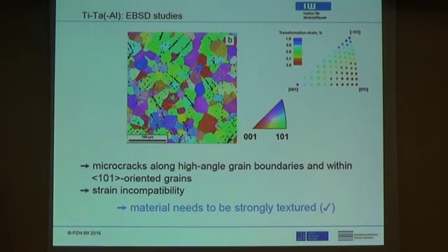And you see that the cracks have a tendency to show up in these green areas. So they do show up in the grains that have this 101 orientation. And up here, this is the theoretical transformation strain. You see the cracks form in those grains that have the large transformation strain. So the problem here is strain incompatibility.